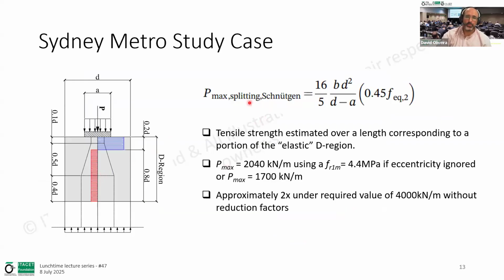We looked at the model by Schnütgen from 2001, which is an earlier model. But one of the things we realized is that it's still based on that elastic assumption, limited to the disturbed zone, which is similar to the linear elastic assumptions. Using that equation with the mean value of FR1. I'm using the mean value here because when it comes to non-elastic or non-linear behavior, most codes will allow you to use mean values if you do full numerical analysis, which we're going to do later. I'm going to show it to you, but for comparison purposes, I'm using the mean value here.